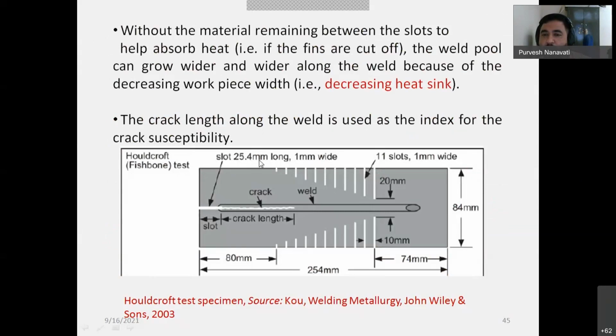Initially a 25.4 mm (1 inch) long and 1 mm wide slot is made so that the crack can be propagated from this end. And you will examine the crack length as you move along the weld. And when you stop over here, most of the time your arc is stopped. So this is the 11th slot starting from this end, right? This Houldcroft or fishbone test: the crack length along the weld is the index for the crack susceptibility, right? The source for this is Sindo Kou, Welding Metallurgy.